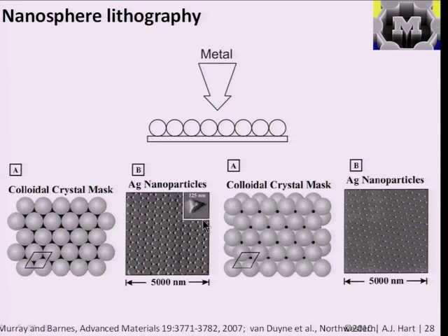Another thing that can be done is there are ways that these groups, and there's one group, Richard Van Duyne's group at Northwestern, that invented this and has really taken it to the limits to understand the fabrication and plasmon resonance. They can deposit another layer of spheres on top before they do the metal deposition, and then they end up with dots that are smaller and more separated.